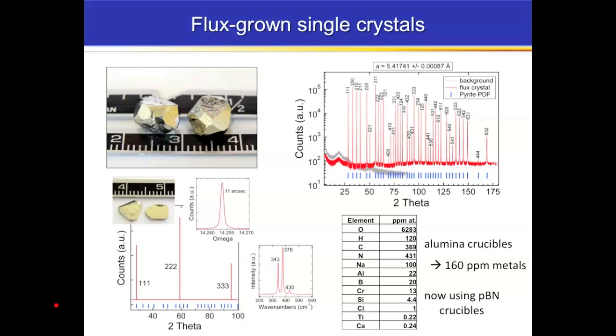Okay. In addition to the thin film materials, we also spent a lot of time, especially in the last year or so, working on single crystal pyrite. And so we've developed a new flux growth for pyrite material. We can grow pyrite single crystals that are about 1 centimeter on a side. That's the length scale here. We can cut them up into slices and look at them by X-ray. Rocking curve shows that we have about 6 to 12 or so arc second, full width at half max. And so these crystals are about the same quality as far as XRD goes of silicon wafers.